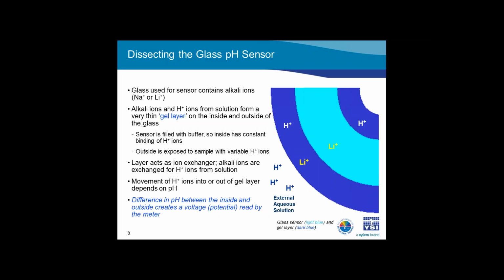With the pH electrode, the glass pH sensor, sometimes referred to as a membrane, is fused to an electrode shaft. The inside of the sensor is filled with a buffer solution of known pH, commonly pH 7. This electrode design creates an environment with constant binding of hydrogen ions on the inside of the glass sensor, while the outside of the glass is exposed to the sample, where a variable amount of hydrogen ions exist. The difference in pH creates a potential across the glass pH sensor that is compared to the stable potential of the reference electrode.